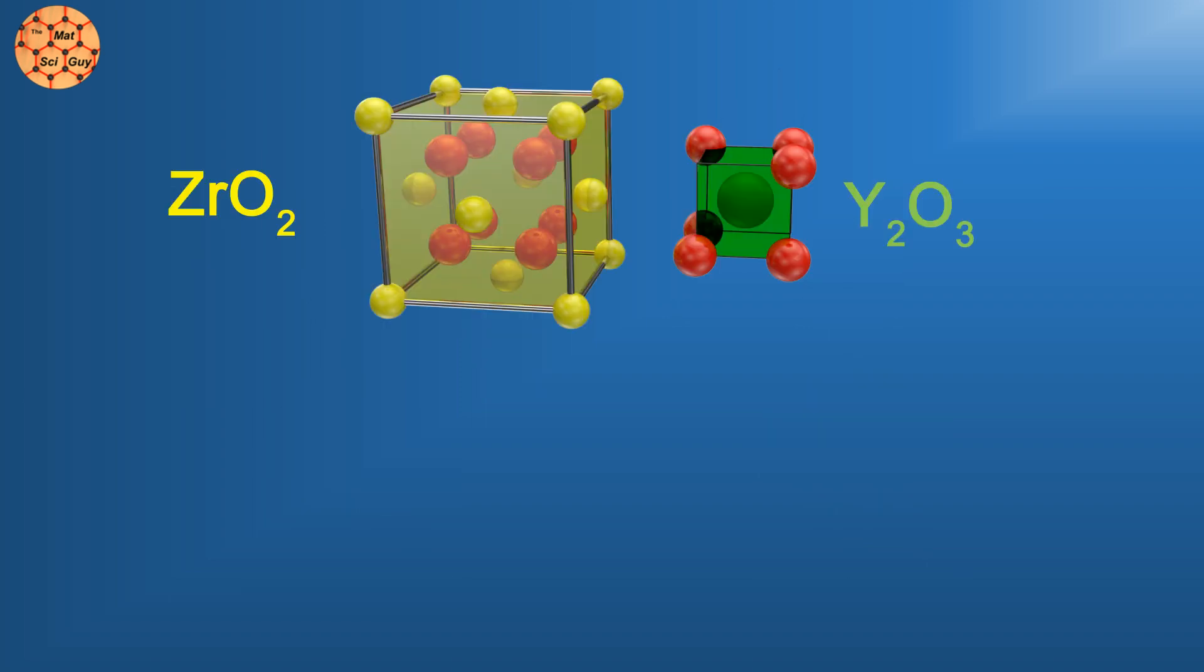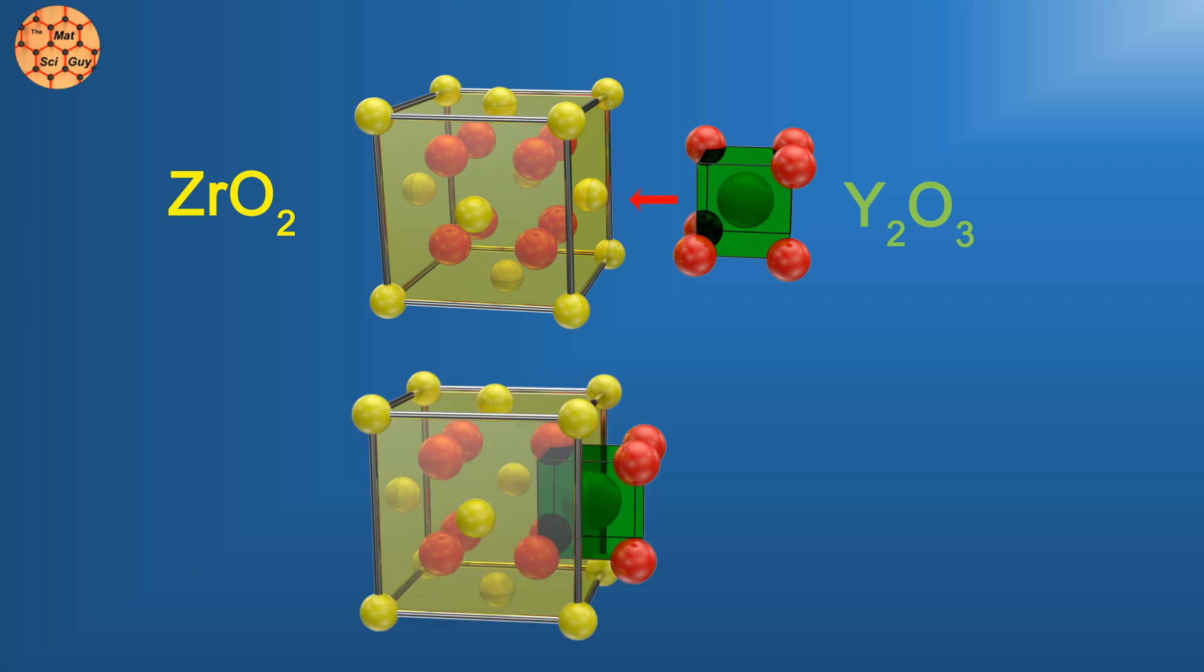In addition, the arrangement of the oxygen atoms around the yttrium ion is very similar in structure to the arrangement of oxygen around zirconium ions, just with some oxygen missing. This stable arrangement of oxygen around yttrium and the larger ionic radius act as a lock for the cubic structure,